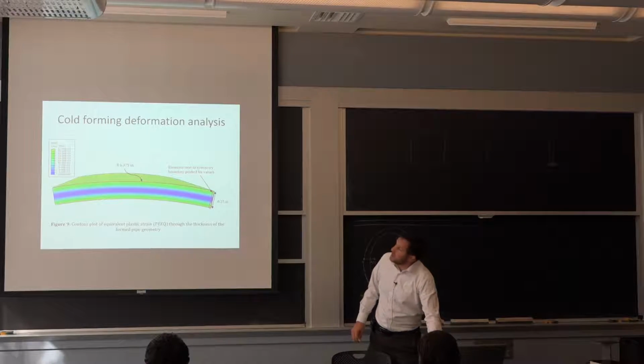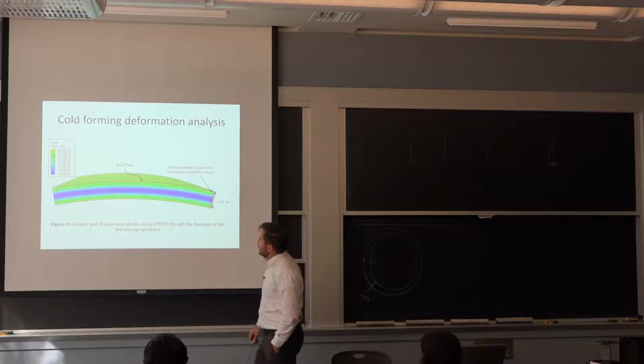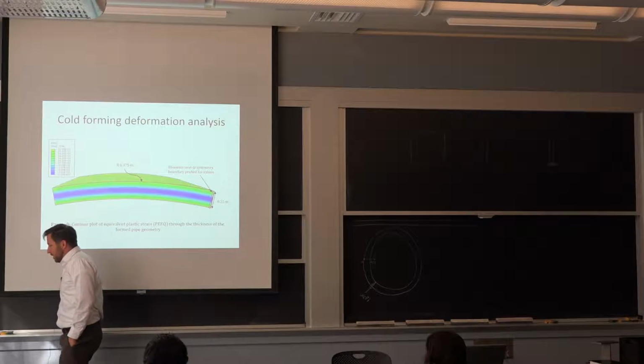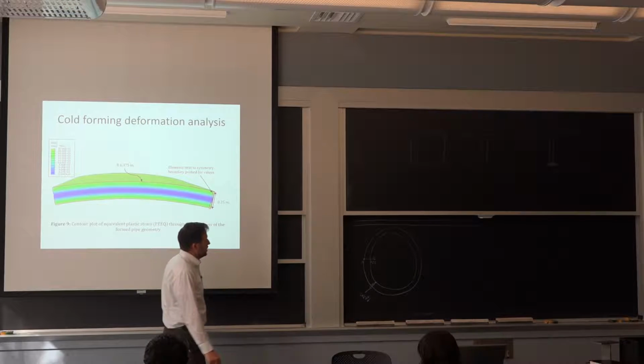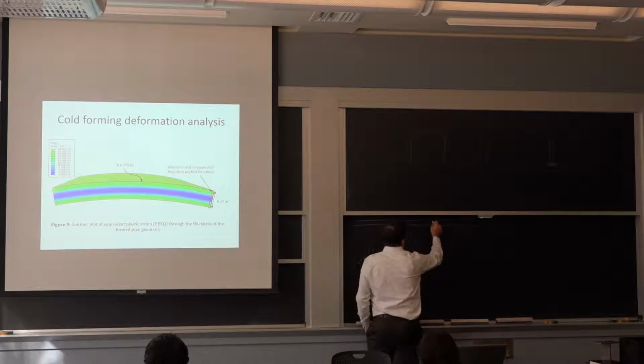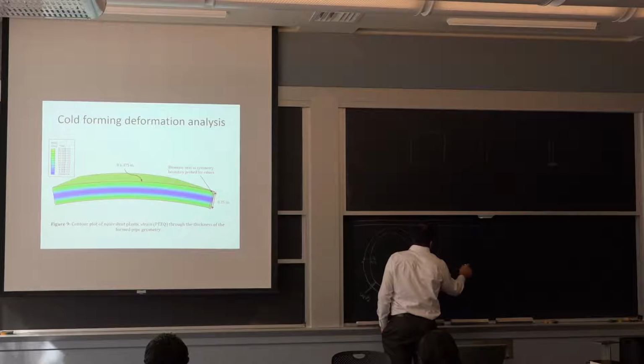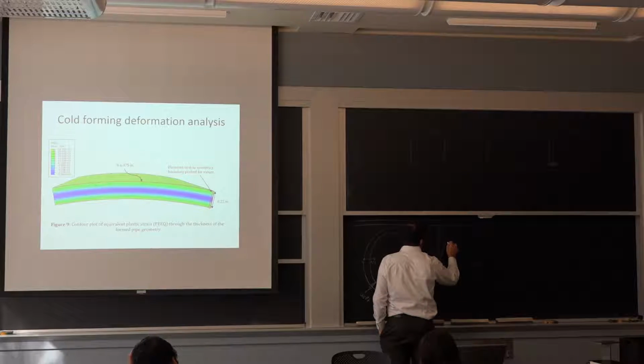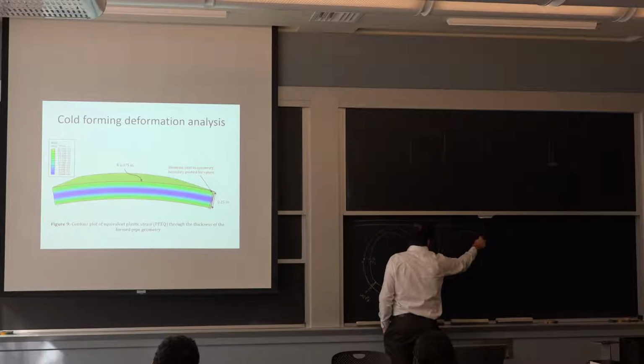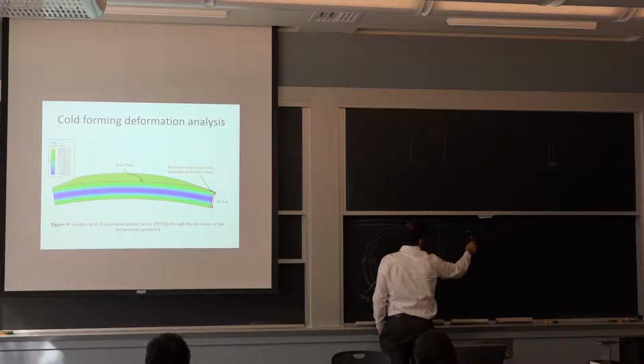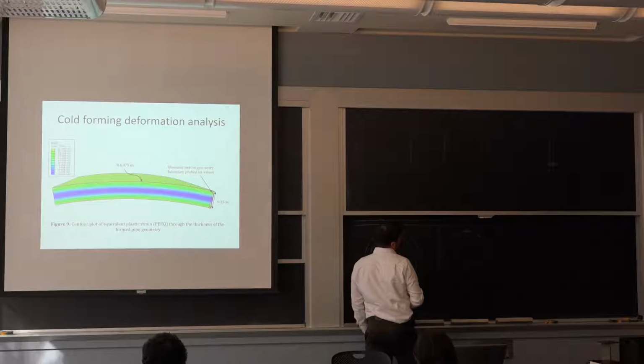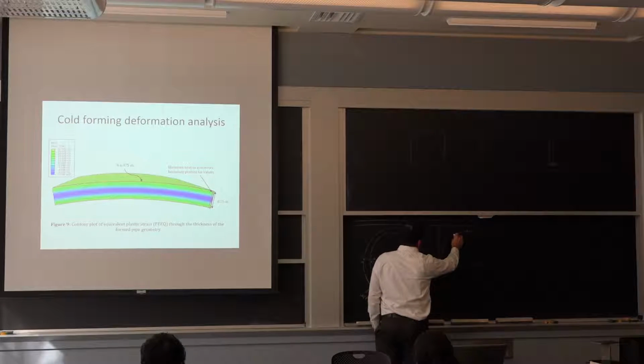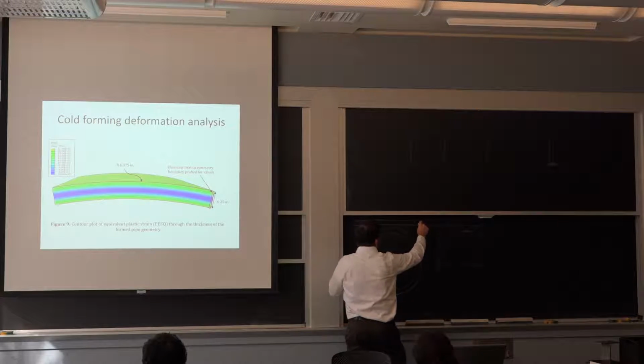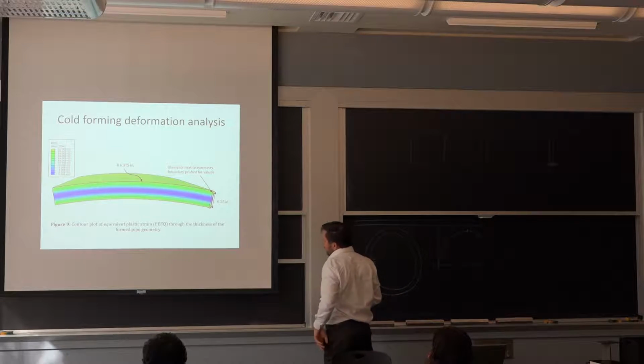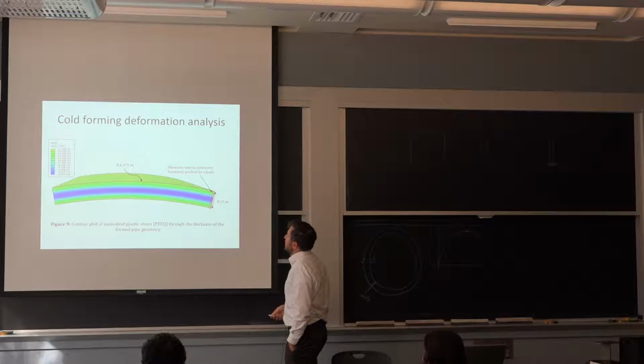So what we did recently is we tested it using finite element analysis. So we had this product here. We did a tensile test on it. So we're getting our stress strain curve to break point. We used the part of the data that is before the necking, and that's what we input into this shape, deform it using laws of physics, of plasticity for metals, and here's what we got.